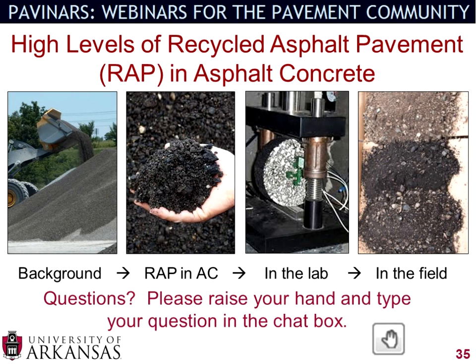And as you get smaller and smaller, it becomes more dusty, and the asphalt cement becomes less valuable because you're increasing your surface area so much with the added dust that you're not really getting the benefits of having that additional asphalt cement. So I haven't seen RAP being used in treatments other than hot mix or warm mix, like those that you were talking about, because of that reason. And the second reason is that you're often using ambient temperatures like emulsions with slurry seals and microsurfacing and surface treatments. So you're not getting the benefit of the RAP, which is that contained asphalt cement.